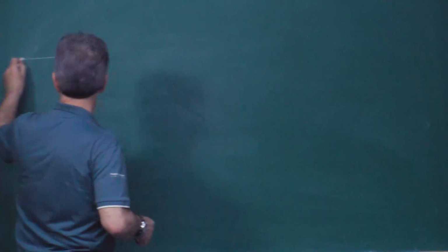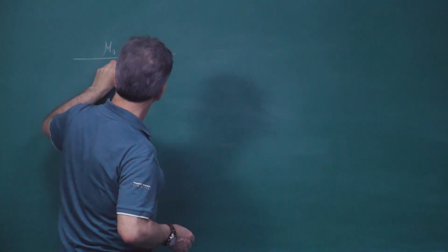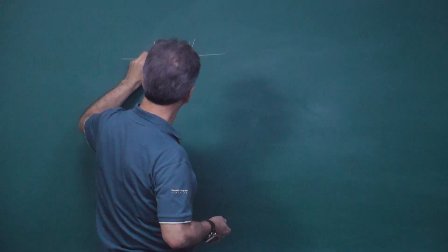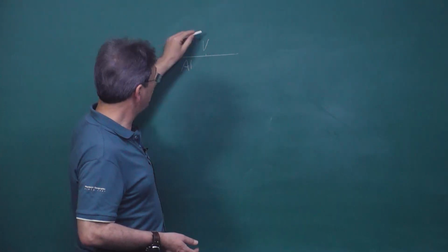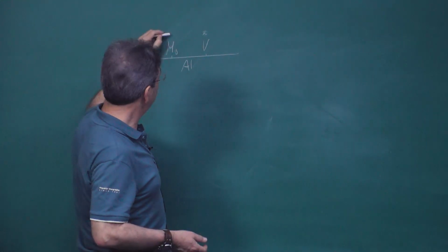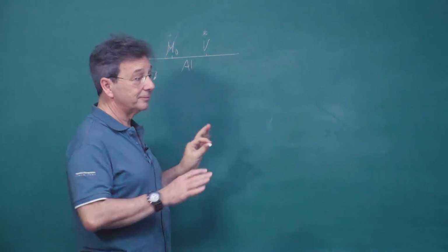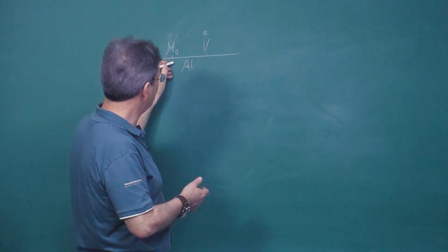You have moly and vanadium on alumina catalyst. At low coverage, basically this one will remain dispersed, this one will remain dispersed, and at 300 plus, this one is doing some activity, this one is doing very little activity, so the presence of this one at low coverage is irrelevant because they are spread and basically this one is hardly active.